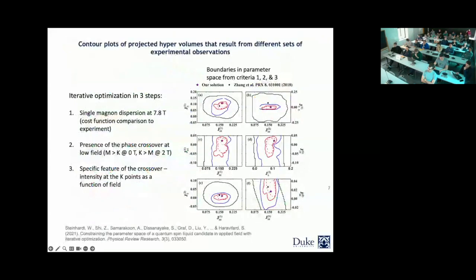So here is basically a summary of what we have done. There have been some single magnon dispersion measurements at about 7.8 Tesla, where we looked at the cost function comparison to the experiment. But as I said, this was very diffuse. And then we looked at this crossover as well. Here we are showing what were the proposed values for the different exchange parameters initially, and these are how we were able to constrain the order parameter space based on the transitions that we saw as a function of magnetic field. I'm not going to get into too much detail about this. If you're interested, this was published a while ago. Please have a look at this or talk to me later on.